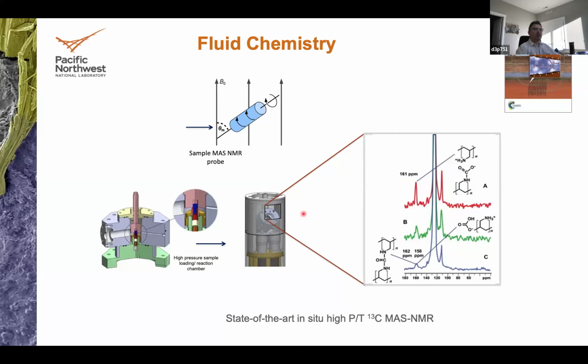It's spinning at high frequencies, and then you add the CO2, and what you can see is what's going on with the chemistry, where you form an ammonium carbamate, so a protonated amine of the polymer reacts with the CO2 that is already linked to a second amine, and then it cross-links, forming a reversible ammonium carbamate. That's the reason for the reversibility of the process on the volume expansion and the viscosity increase.